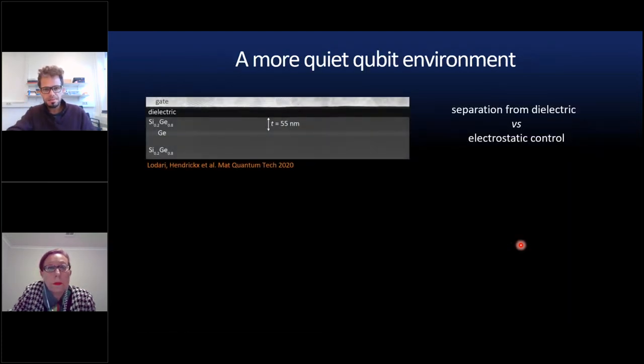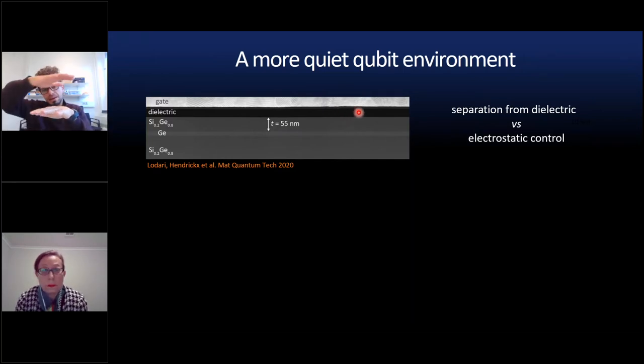Here, the last thing I want to talk about is, once we have qubits, and here again it's the importance of materials, to then go back and really tailor your material to advance the properties of the qubit. So we've done this, and we actually published this result in Materials for Quantum Technology by playing with the depth at which we position the quantum well. And here, there is a trade-off between separation from the dielectric interface. So you want to have it deep to be away from the nasty interface, but at the same time, you don't want it too deep that you are losing the control that you need with your gates.